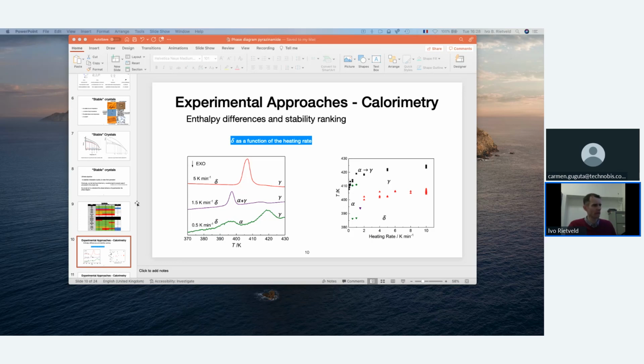Obviously, this is the behavior of the delta form. What you can see as a function of the heating rate is that if you go relatively fast, delta will immediately convert into gamma. Going slightly slower, this delta form will form alpha and gamma. This we also checked with X-ray diffraction, which I didn't show here. And you can see here a little bump, I hope. That is the conversion of alpha into gamma, and going even more slowly, delta will turn into alpha, and then turn into gamma. And that is shown in the graph on the side.